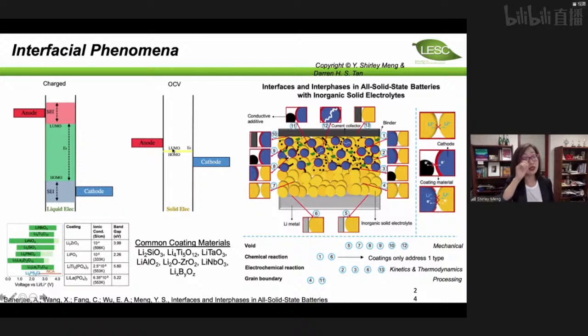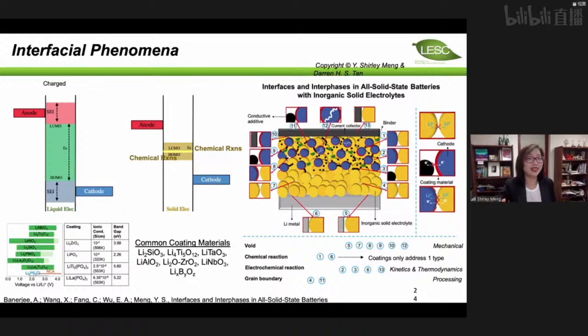Lithium is indeed stable with LLZO, a garnet-type solid electrolyte, but that's a very rare case, right? So number one, material scientists have to think about how to make them chemically compatible to stabilize the lithium metal anode in the solid, okay? Number two, of course, you have another challenge. The solid usually has a very narrow electrochemical window, so you still have the SEI challenge.